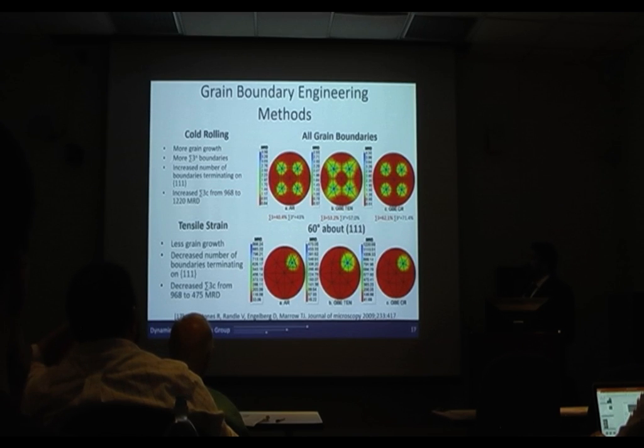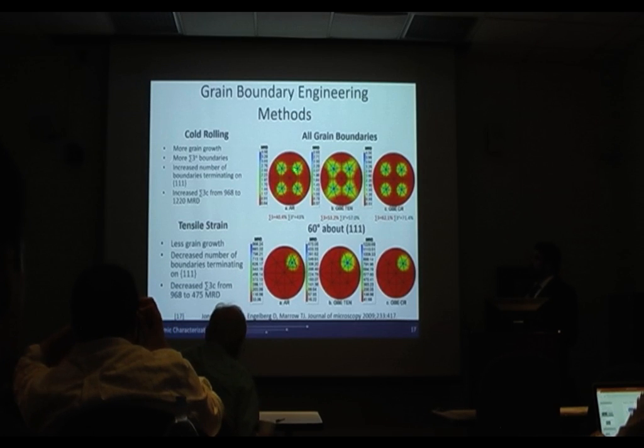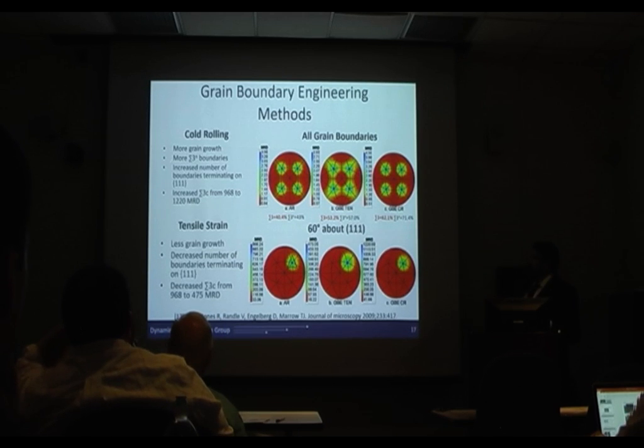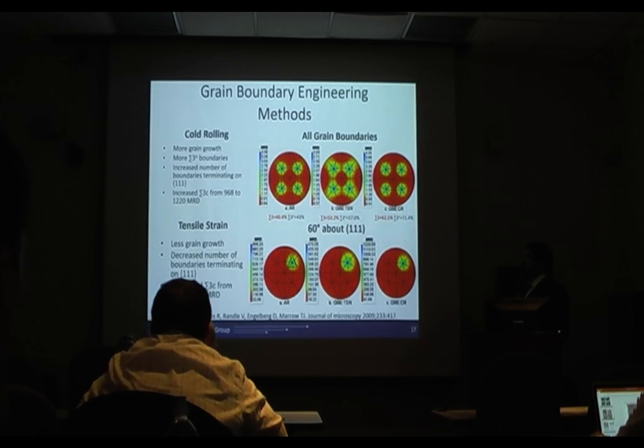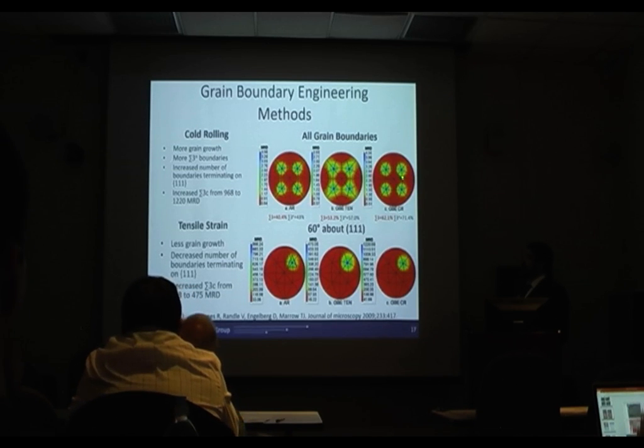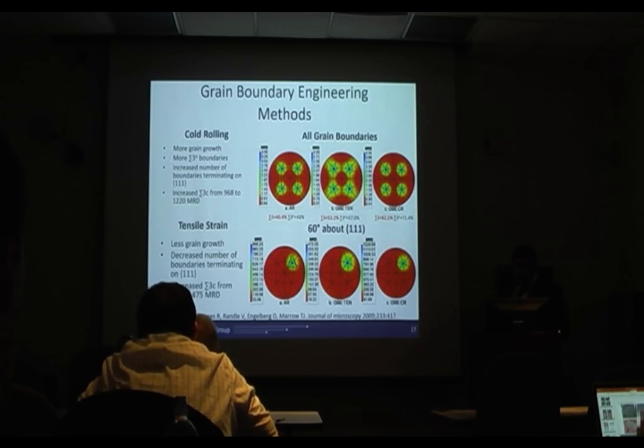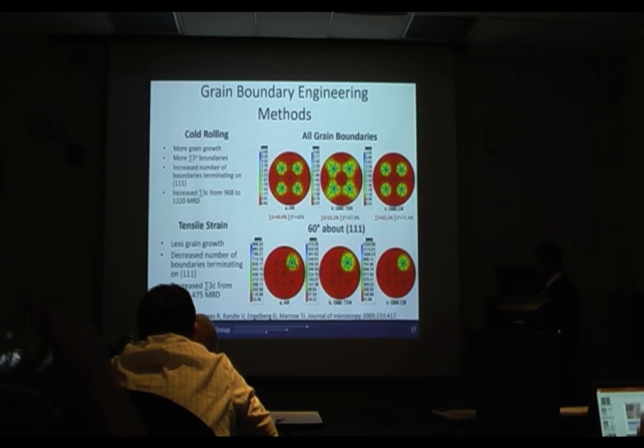And what you can see is that when all grain boundaries are taken into account around the 111 pole here, it's about 3.56 for the as received. For the tensile, it's actually dropped, and this indicates that the level of coherence of the twins present has actually dropped, and you can see that there's greater spread in this microstructure as well. And then in the cold rolled, it's actually increased above the annealed. So by using these two processing routes, you can actually compare the coherence. And in the 60-degree rotation about 111, we see the same sort of trend. And there's slightly different grain growth as well.